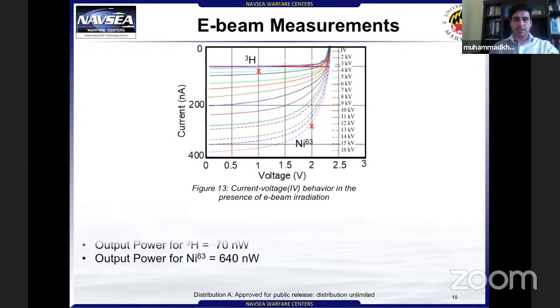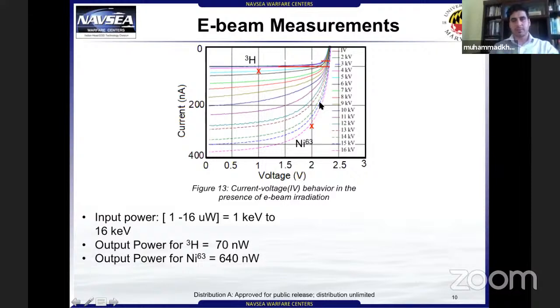Since we did not have access to beta sources in our lab, we tested our devices under an electron beam system. The electron beam system emitted electrons at different energies, and we performed a sweep from 1 keV up to 16 keV. This is the output that we got. As you can see here, the IV curve dropped further and further into the fourth quadrant as the input energy of the E-beam was increased.